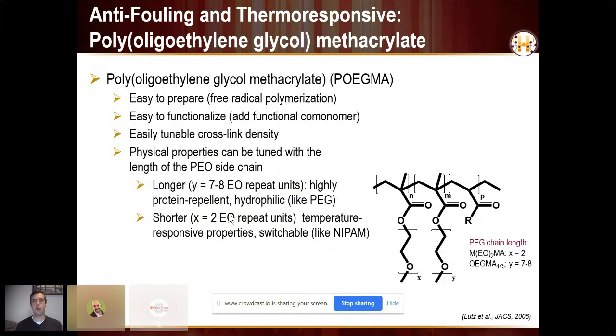The other key benefit is that depending on the length of the side chain, so the values of X and Y in the chemical diagram, we can dramatically change how this polymer behaves in solution. If we have a short number of repeat units, so 2 repeat units, we get temperature responsive properties, very similar to those of polyNIPAM. If we go longer, so a minimum of 5 to 6 units, but longer still, because there are commercial monomers available up to 40 units, we get highly protein repellent hydrophilic properties like PEG. But interestingly, there have been reports that there's no immune response to this brush PEG-like structure like there can be to the linear PEG. So there seems to be a differentiation depending on how the PEG is presented to whatever PEG antibodies may be present. So this polymer solves a lot of our synthetic challenges, but also allows us to really adapt the polymer for different uses.